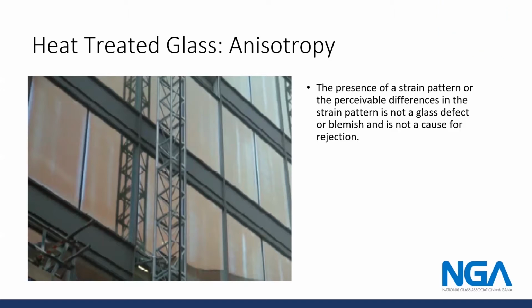During the quench process, the air is supplied through nozzles or slots to the glass surface. So differing levels of stress on the glass surfaces can occur during the quenching process. And also if there's non-uniform heating in the furnace, it can also contribute to the iridescence or the quench patterns. So that's why when you look through certain types of lighting conditions, you're able to see lines like you have on the screen, or sometimes you're able to see dots on certain different conditions. So that is anisotropy. So is it inherent in the process?